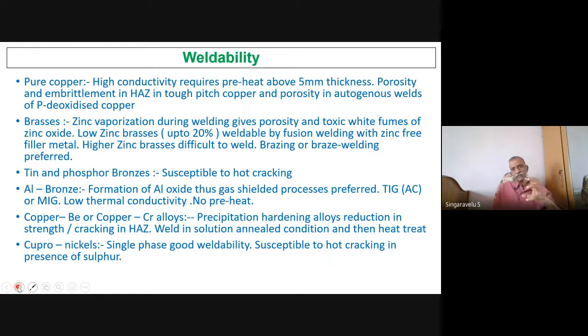Coming to the real weldability characteristics of these alloys, what you have seen there, from pure copper to various brasses and bronzes. Pure copper, high conductivity, requires preheating above 5 mm thickness. Porosity and embrittlement in the HAZ in tough pitch copper, and porosity in the weld in phosphorus deoxidized copper. You have to preheat beyond 5 mm, right? In the brasses, zinc vaporization occurs. Brass is an alloy of copper and zinc. The zinc vaporization gives the porosity and toxic fumes.